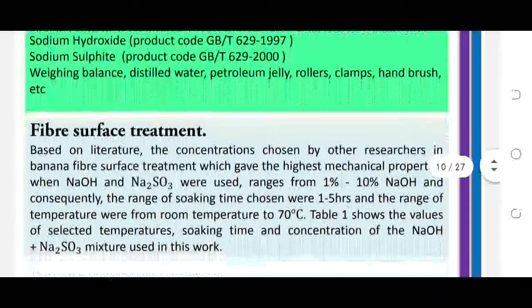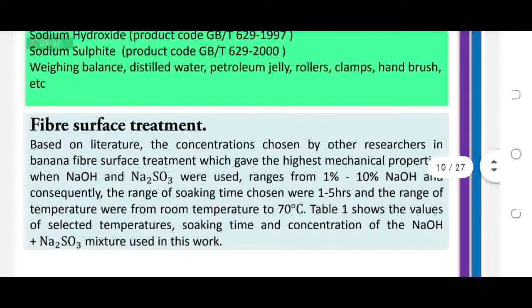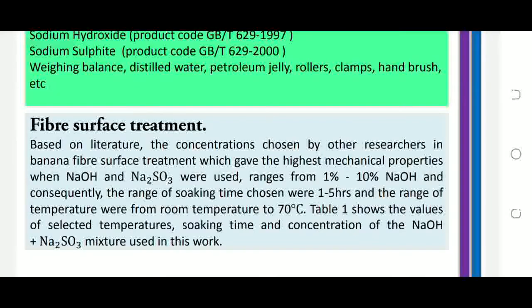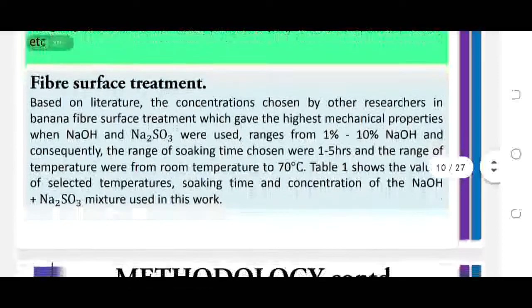So, the fiber surface treatment. How we selected our parameters is based on literature we reviewed, the concentrations chosen by other researchers in banana fiber surface treatments, which gave the highest mechanical properties when sodium hydroxide and sodium sulphite were used, with concentrations ranging from 1% to 10%. Consequently, the soaking time ranged from 1 hour to 5 hours, and temperature ranged from room temperature to 70 degrees Celsius. So this helped us to determine the range of parameters which we chose.